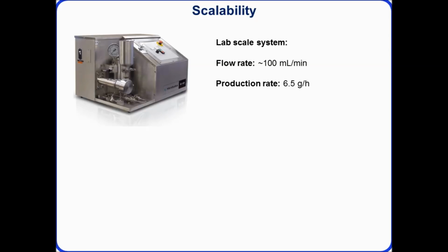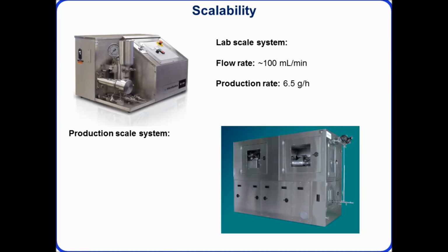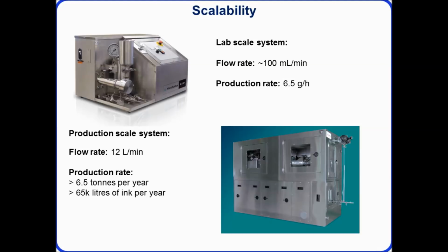However, if we were to look at scaling this process and go to one of the bigger microfluidic systems where we have 12 liters per minute flow rates, then our production rate can scale to around 65,000 liters of graphene conductive ink per year, or 6.5 tons by mass of the graphene alone. So that's a huge amount of throughput on one microfluidic system.